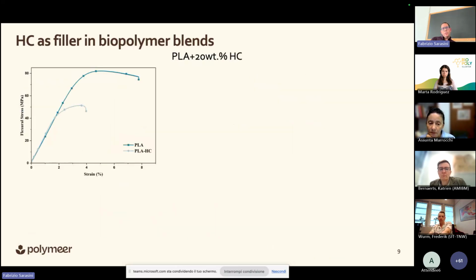So the next idea was, okay, let's try to reduce this effect, maybe taking advantage of the extensive functional groups present on the surface of the hydrochar. Just to mention that, as you can see here in the bending properties, the significant reduction in the molecular weight also resulted in a significant reduction in the mechanical properties of the composite.